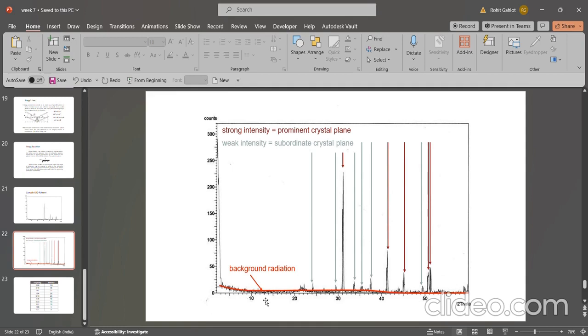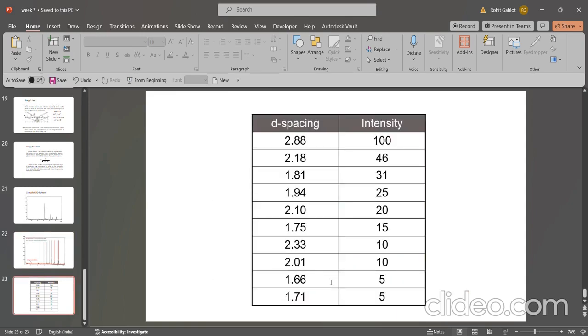And then this is the background radiation. It can be subtracted during analysis. After analyzing, we get that for a d spacing of around 2.88, the intensity maximum is around 100, and for 2.18 around 46, and so on.